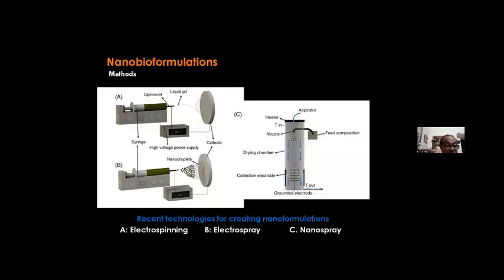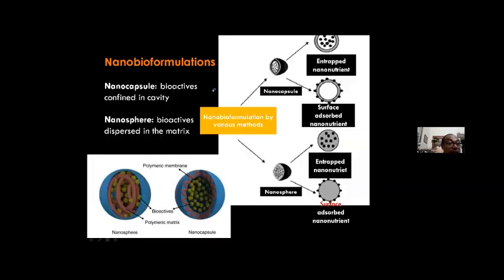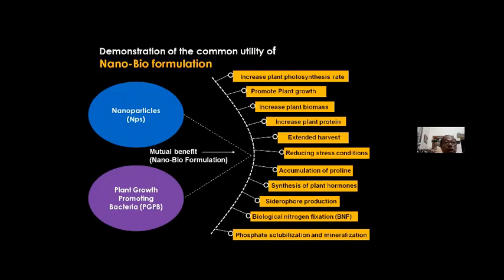This nanobioformulation you can very easily make in your laboratory by using electrospinning, electrospray, or nanospray. You see, you can make nanocapsules where bioactives are confined in the cavity, or you can make a nanosphere where bioactives are dispersed in the matrix. So under nanocapsule, the nanoparticles may be entrapped inside or surface adsorbed. In the case of nanosphere also, they may be entrapped inside or surface adsorbed. So what additional advantage are we getting with this formulation?